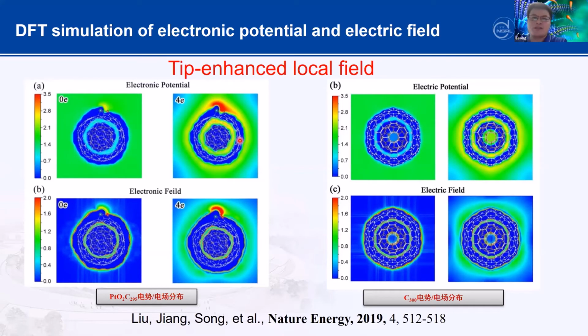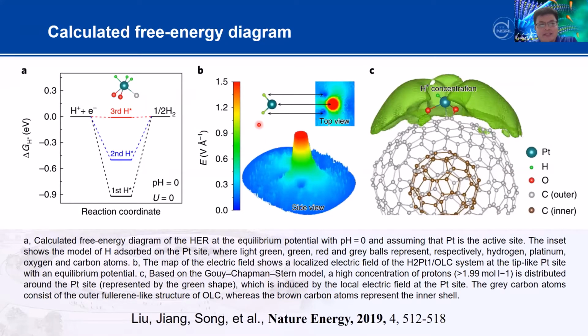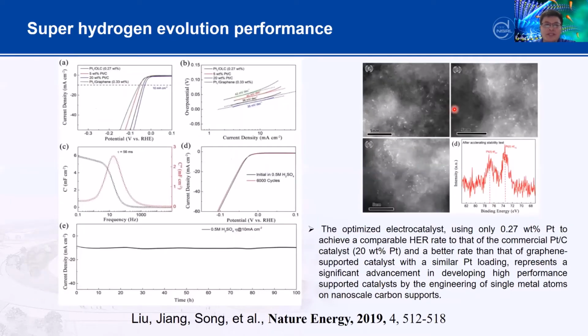So how does this work? We calculate the free energy diagram. We found if you have this kind of structure and you try to put the proton in here, since this is a local field, if you put 1, 2, and 3 protons in there with electrons, you really see two protons can combine together to form hydrogen. So that means this local structure really contributes to the hydrogen evolution. So this is the experimental result. As you can see, this single atom is really stable.